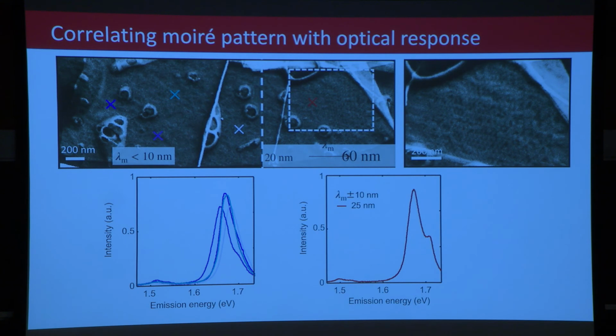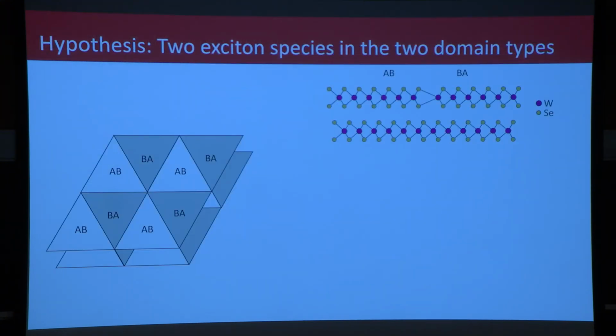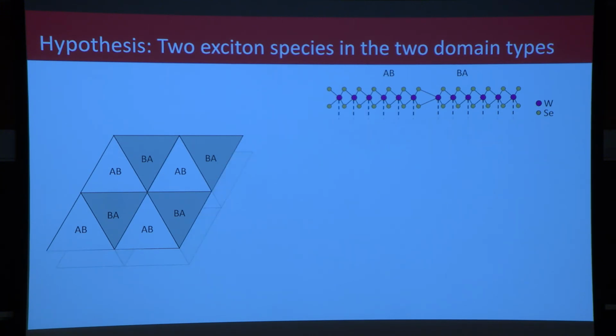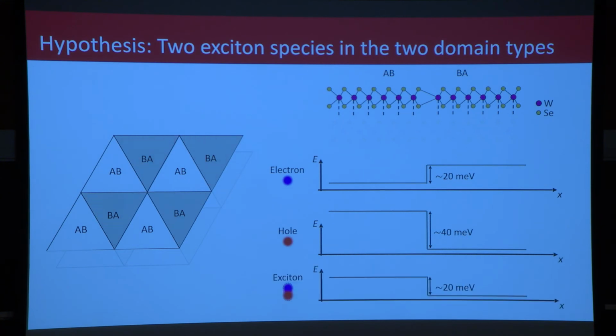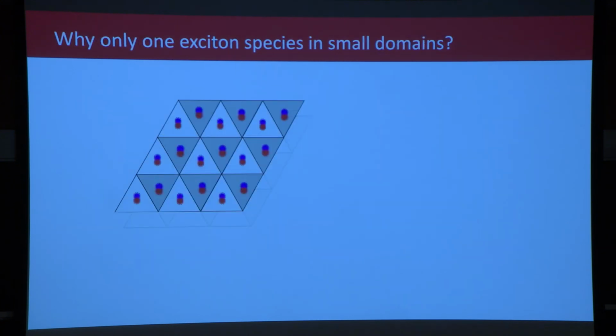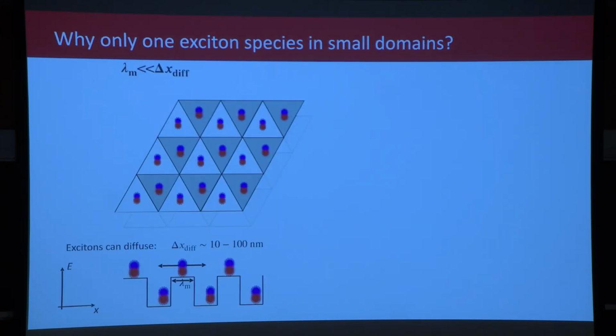But basically, we can change the Moiré spacings, and then we can see how the spectrum changes. These spectrum changes are best explained by the exciton diffusion in these monolayers, both in between the layers and within the layers. So we believe that what we are seeing is exciton diffusion in these systems, and we can study them as a function of the Moiré pattern size, and how it changes and what have you. So all those things can be studied, yes. If you are interested, I can show you more data about that, but I didn't want to make a 2-hour talk, so I decided not to talk about these.